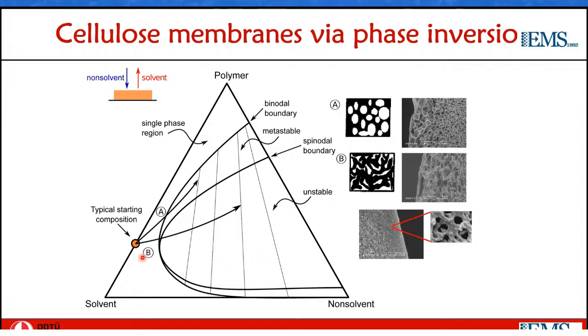When this happens, the starting composition starts moving to the two-phase region of the phase diagram, and there's phase separation occurring into a polymer-rich phase, which eventually forms the membrane matrix, and the polymer-lean phase, which eventually forms the membrane pores. Depending on where the starting solution is compared to this binodal boundary and the non-solvent in-diffusion rate and solvent out-diffusion rate, the morphology of the membrane is determined.